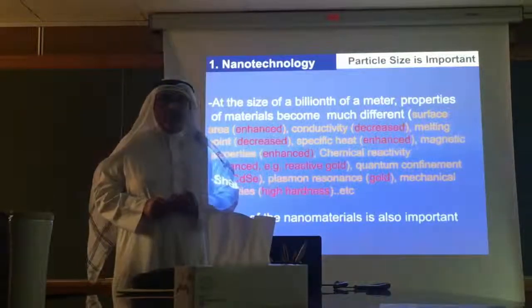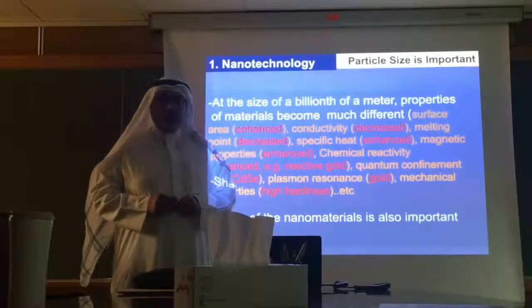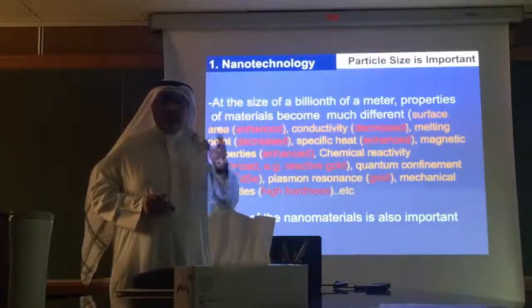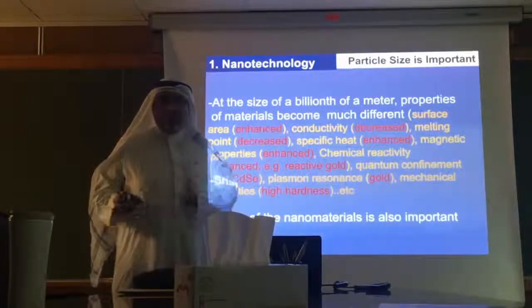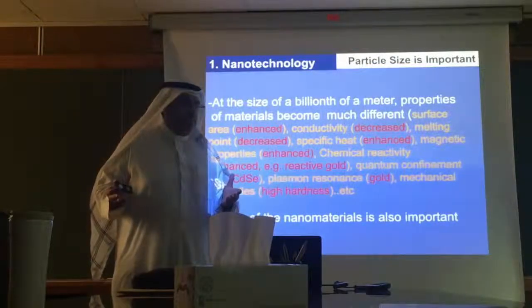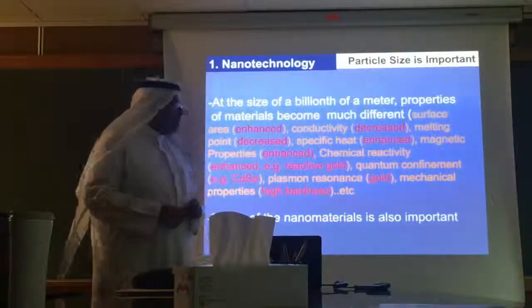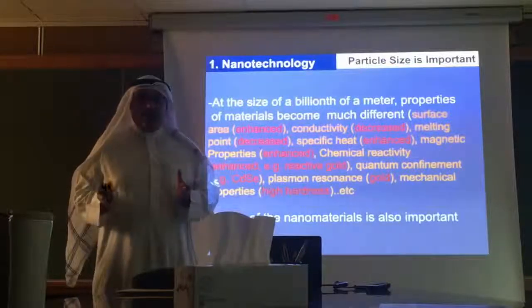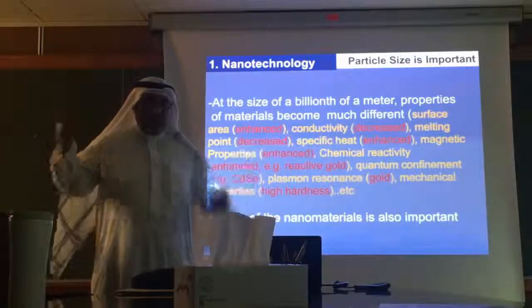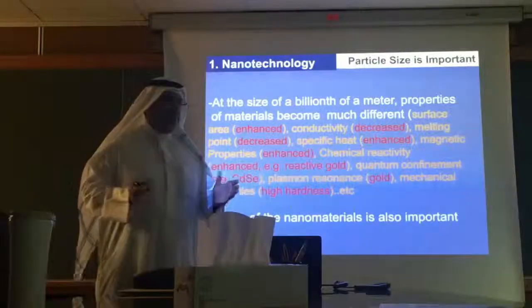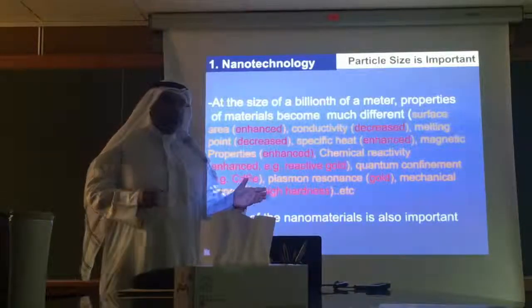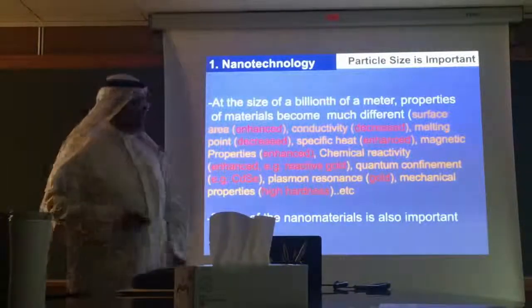For example, for gold, we don't get the interesting result unless we make the gold less than 5 nanometer. Even 6 nanometer will not give us a very interesting result. So when we say 1 to 100, this is, let's say, the frame, but for some material it has to be smaller than that, much smaller than that, to get the fascinating properties.